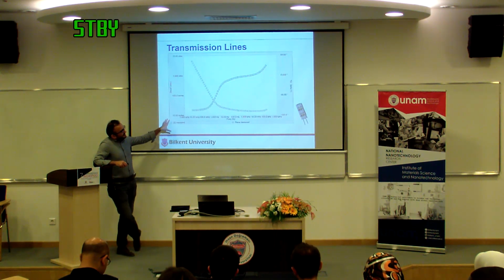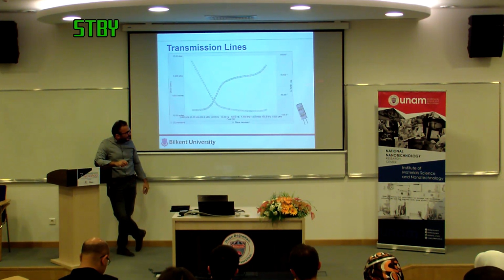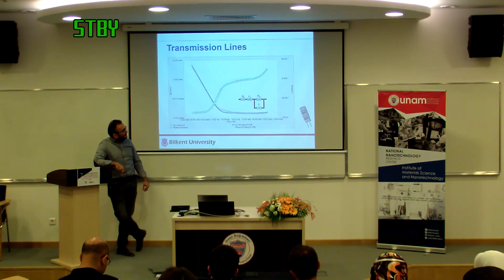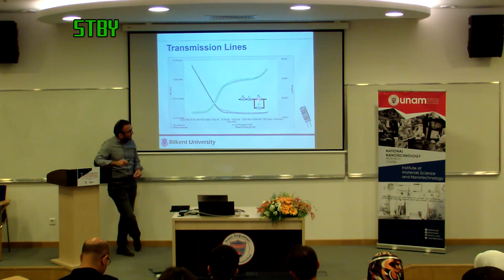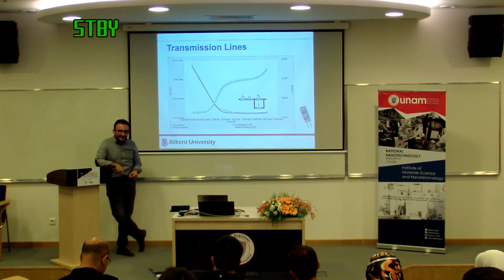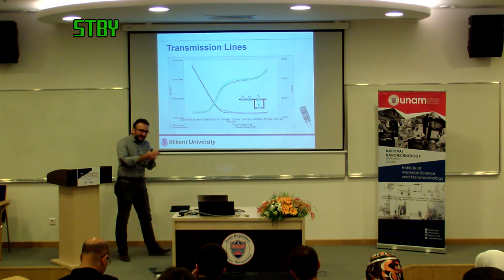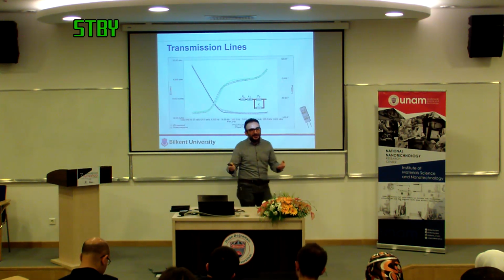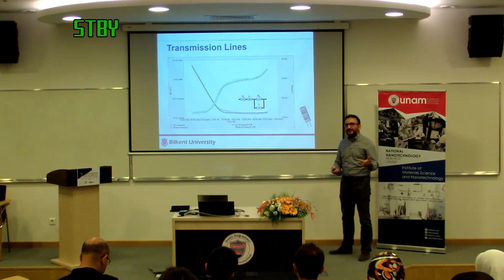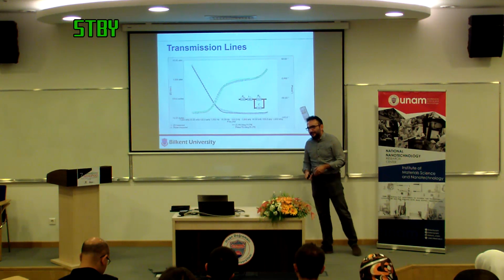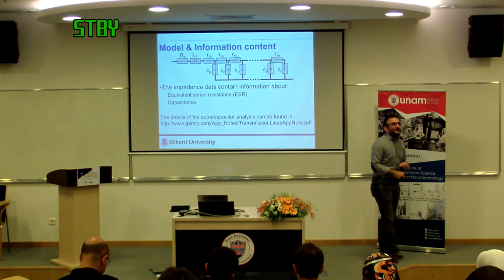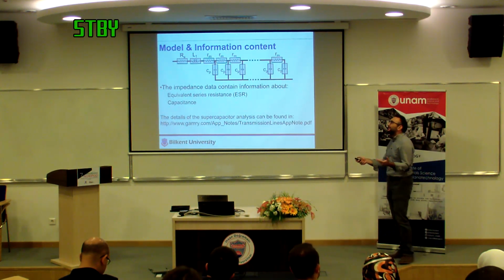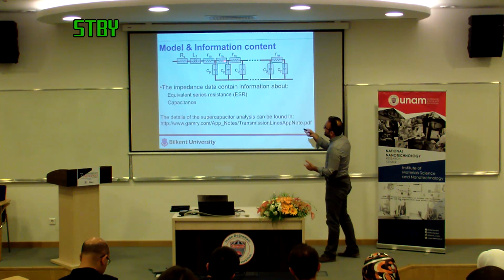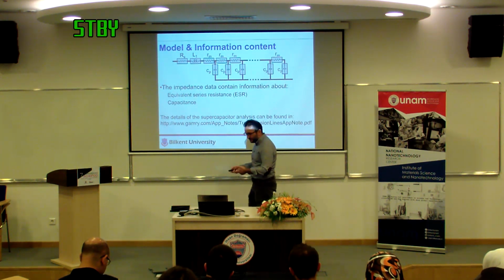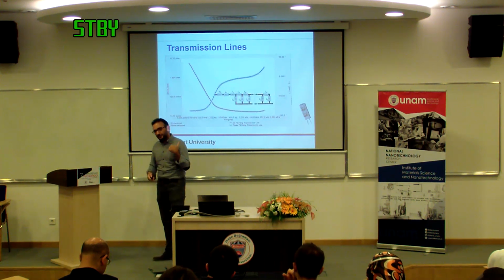So this is the simplest porous electrode that I can find. It's a supercap, and this is what the data looks like. And if you try to fit it with standard elements like your R and C, you capture the bulk, but you notice that there's actually a transition that you miss. And the reason you miss it is because there's a distribution of these R's and C's that your model does not have. Your model only has one R and one C, but the data has a distribution of it. So you have to resort to math to actually be able to grab that distribution of time constants. You have to think of infinitesimal R's and C's and then integrate them under certain conditions, and your fit goes from this to that.